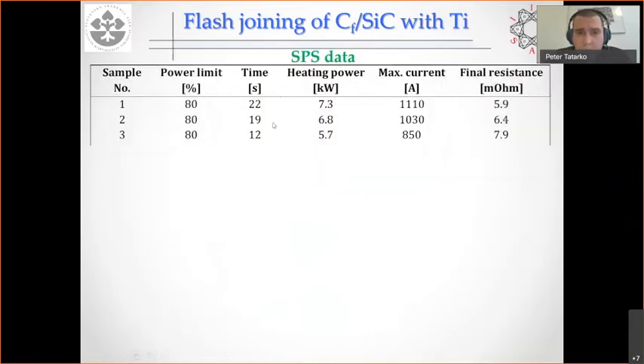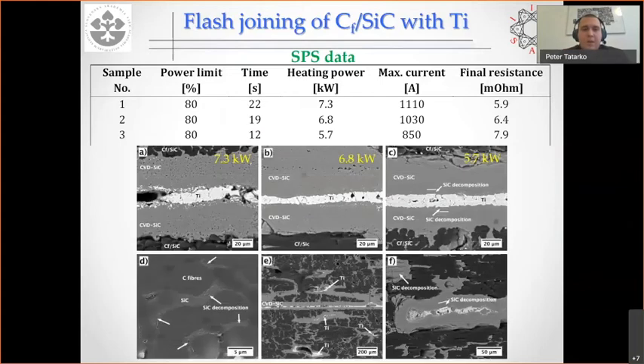In our SPS machine, we could only control the power by setting up the power limit. So we set the power limit to 80%, and we interrupted the process after different times. Here 22 seconds, 19 and 12 seconds. Of course, the lower the time, the lower the heating power, and the lower the current. In all these three cases, we obtained joints. After joining, the material could be cut, polished, and then looked at by SEM. But the problem was, if you see here, this is for sample number 1, 2, and 3. You see the power is decreasing.